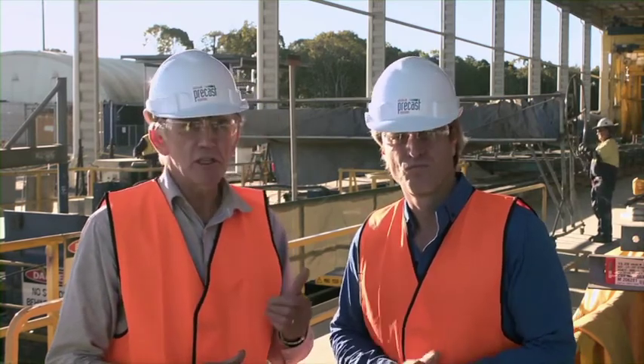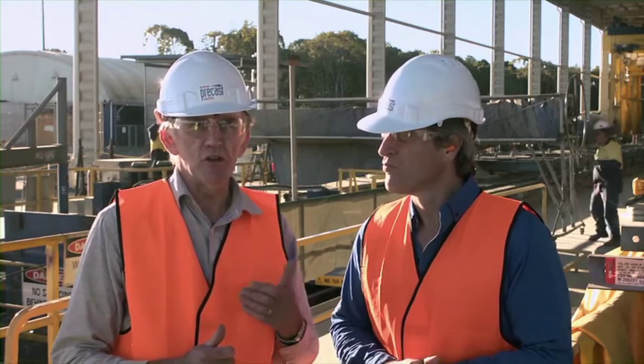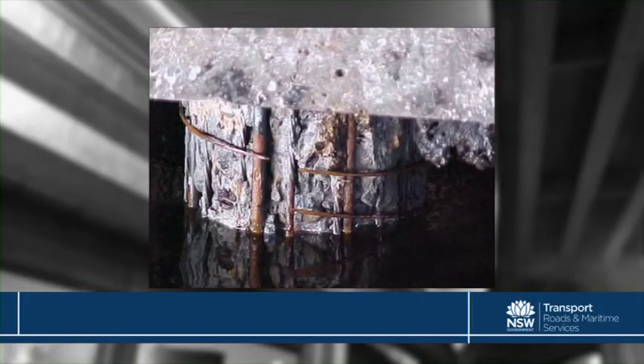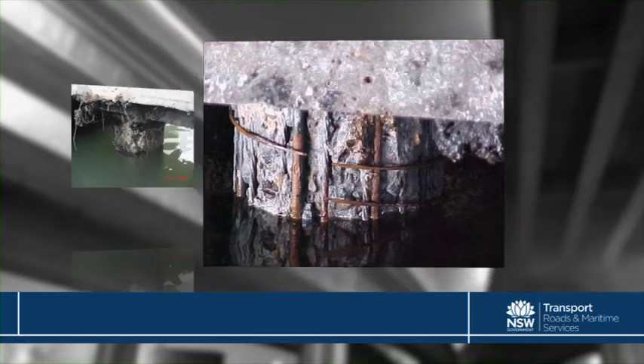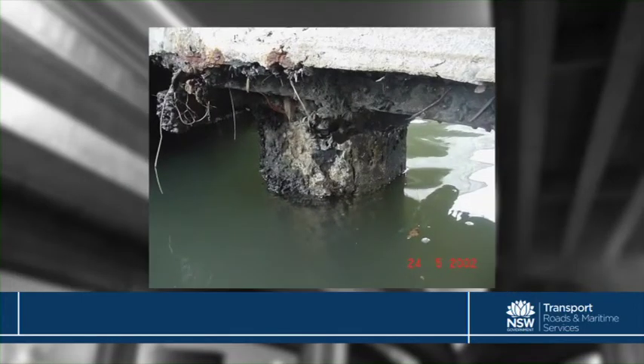Now, this is because this form of curing has the potential to cause cracking damage to the product or cause a phenomenon known as delayed ettringite formation, or DEF, which happens later in the product's life. DEF will expand and destroy the concrete as a protective member for reinforcement steel. DEF occurs when the curing temperature exceeds around 70 degrees C and other factors such as moisture are present. Hence, there are general limits in B80 about heat accelerated or steam curing.